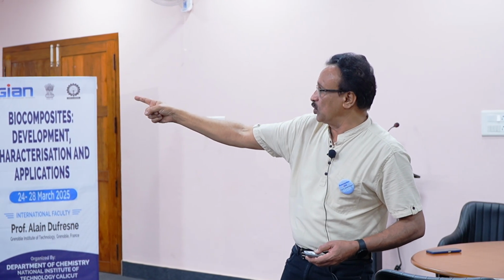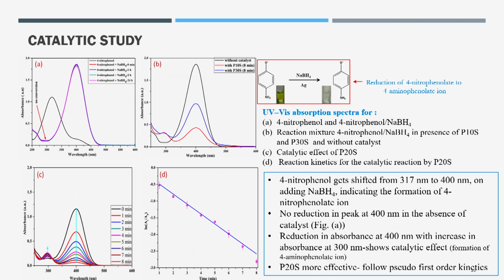The second graph is with P10S and P30S. There also, you do not see a significant signal at 300. It means the product has not been formed. But if you look down, that is the catalytic activity of the reactant with P20S, 20 percent of that. See, the 300 signals are there. Only in that graph where P20S is used, 300 product signals appear in UV visible.